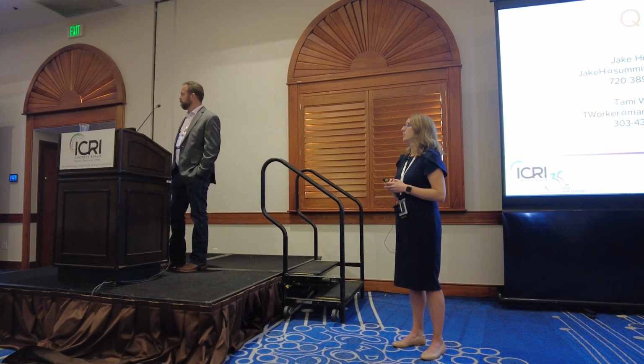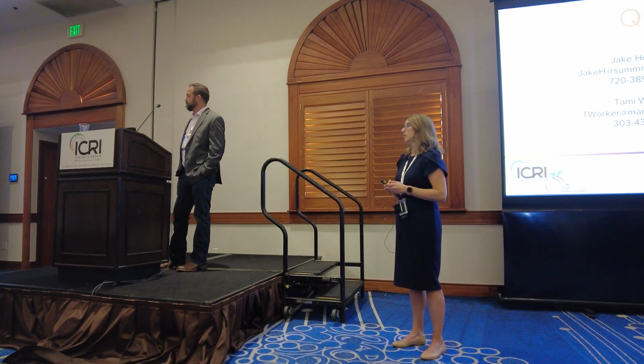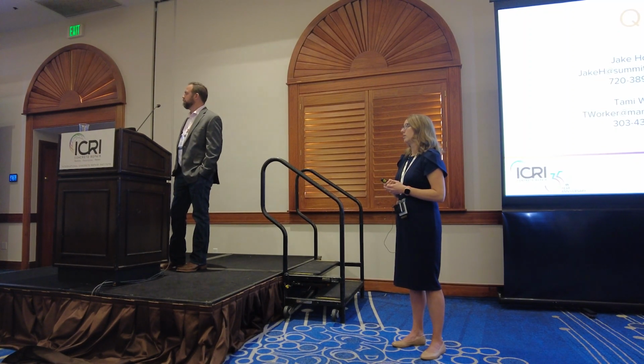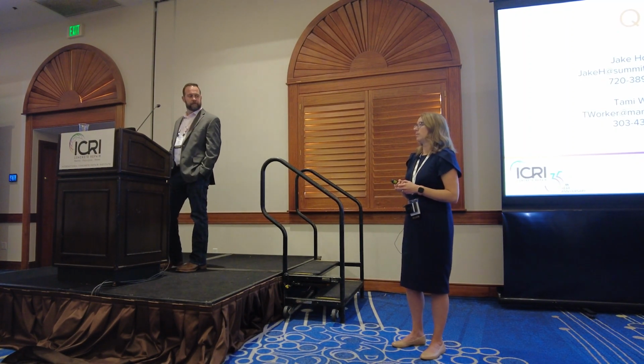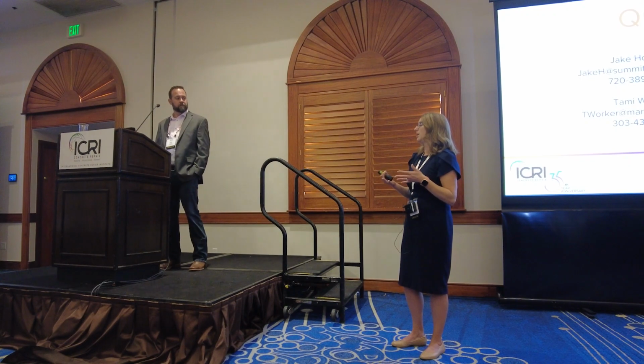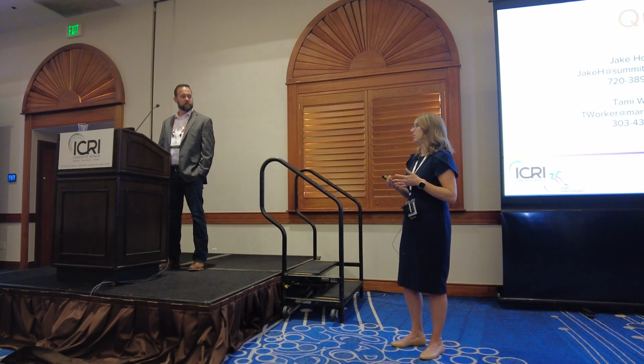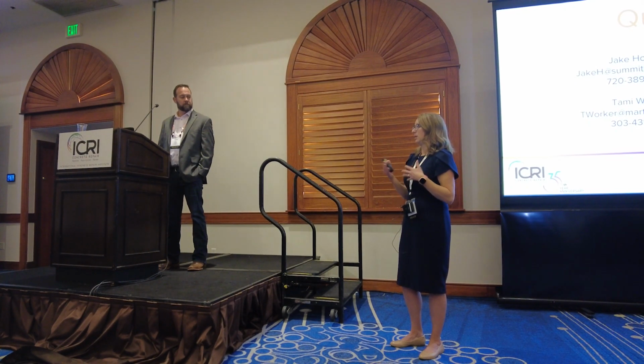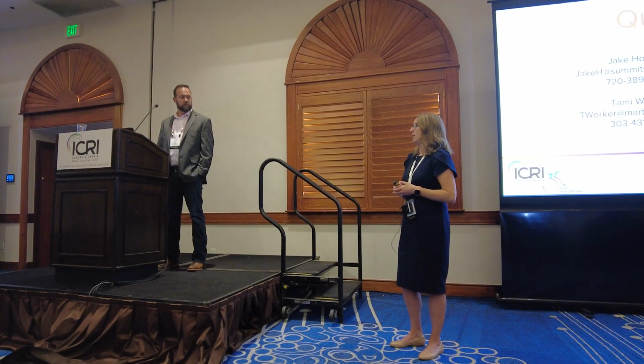Yeah, I was referring more toward the preparation of the substrate for the FRP. So really what you need to do is you need a sound substrate to apply to. So sounding the material is critical. If there was any honeycombing or something, that would need to be addressed. But yeah, that test is not usually required unless there's some sort of visual indication that the material isn't sound.